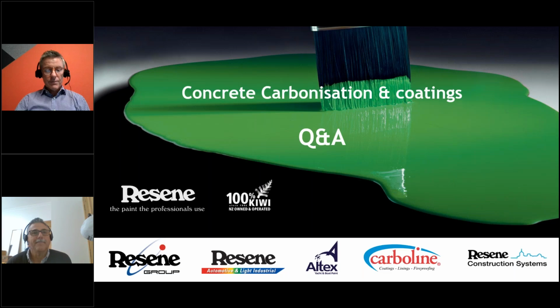Sarah Foyne's come in asking, what does Resene offer to control efflorescence? Well, we have a product called HydroBlock. Ideally, you want to deal with the cause of the efflorescence, the water, where the water is getting in. Once you've dealt with the source of the ingress, or maybe you can't and it's just minimal, then if the wall is unpainted, you can put on HydroBlock, which will hold back a significant amount of moisture and efflorescence and keep the wall looking dry, and then you can paint over HydroBlock, which is a clear. It can't handle water being forced through the wall, but if the wall is just looking damp and dark and efflorescence is coming through, that's a good option.